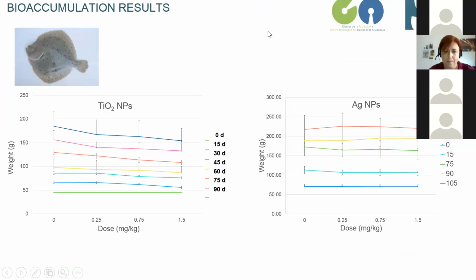Well, first thing to comment is that in the exposures performed with turbot, we observed that during the experiments there were not significant differences in the weight gain. During the exposure, the turbot were fed with these pellets containing the nanomaterials or not, as in the control, and they were gaining weight as usual.